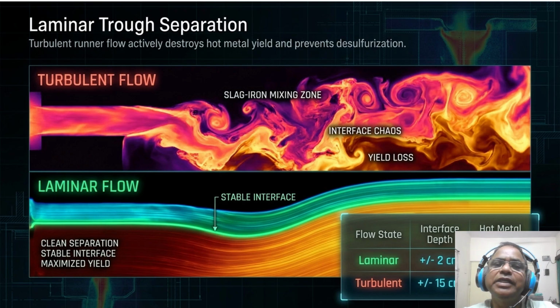So for a 3 million ton per year furnace, that 2.4% difference in yield is pure profit lost to the slag pit. So stable furnace dynamics are the final step in securing the economic value of your hot metal. Unfortunately, when things go wrong, operators often reach for the oxygen lance, a move that carries a heavy penalty.